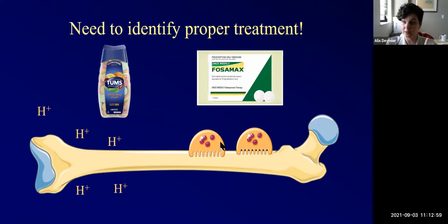But if it's the cells, you'll probably want to give them a bisphosphonate. A bisphosphonate is just a drug that stops osteoclasts from dissolving bone. If you do that, you should be fine. You can treat the acid later, but you can immediately stop the skeletal response. So we really need to understand which of these mechanisms is occurring, which one is causing the worst consequences, and that will inform how we treat people in the future.